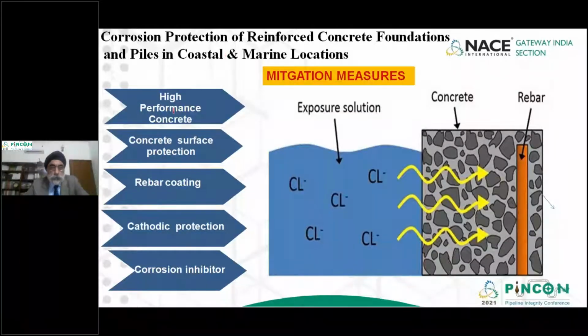So the basic strategies which anybody would adopt is to use a high performance concrete which would inhibit moisture and chloride ions from hitting the rebar, and provide coating between the concrete and the soil surface, called concrete surface protection. The third strategy would be to do a rebar coating. That means you coat the rebar. The fourth strategy would be to do cathodic protection of the rebar. And the fifth strategy would be to put corrosion inhibitors in the concrete, which would keep the surface of the rebar passive.